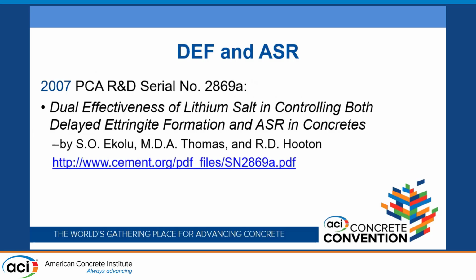Another example for Michael, moving on from DEF and his other favorite subject of ASR, he did a lot of work on lithium, and Mike and Doug worked together at University of Toronto, and once he moved to University of New Brunswick. And this report was by his student Ekolu on the effectiveness of lithium in controlling both DEF and ASR in concrete. And it was examined in heat cured mortars that were up to 23 degrees Celsius, followed by steam curing at 95 degrees Celsius, and then stored into a lime water bath. The results showed that lithium salt is able to reduce the occurrence of deleterious expansion from DEF. It also showed that controlling ASR and cementitious environments could control one or both of those mechanisms, which we've known since back in the Stark days.